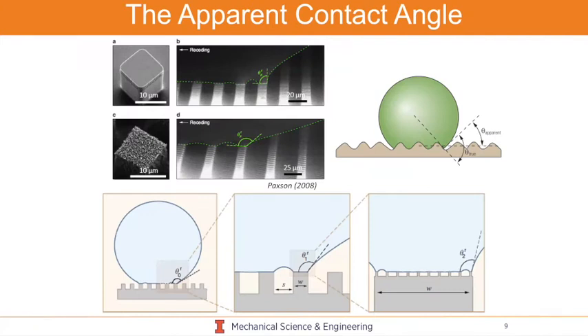So, if you want to think about this more from a fundamental level, you could think about the apparent contact angle or the intrinsic contact angle. So if you were to look at this environmental scanning electron microscopy image, really zoom into that contact line region here at the three-phase contact line. You could actually see that intrinsically the wetting contact angle here is nothing but the contact angle with the smooth surface. But it's only the addition of these air pockets, these are actually pillars, that cause this kind of highly spherical non-wetting state. There's been a lot of work in this area in the past few years, mainly because of interest in how we could use these to dictate some of those transport mechanisms.